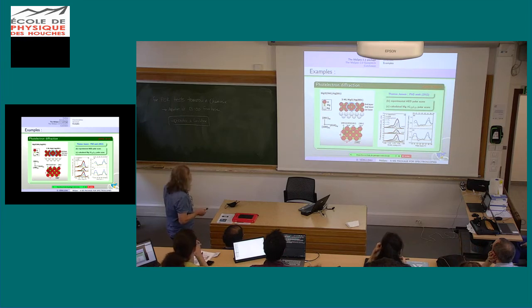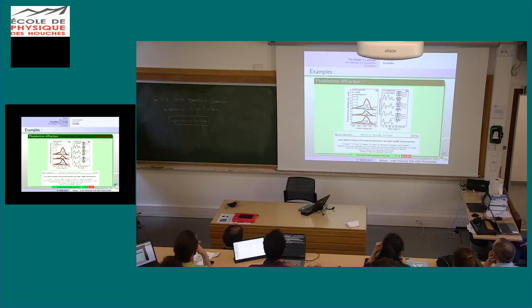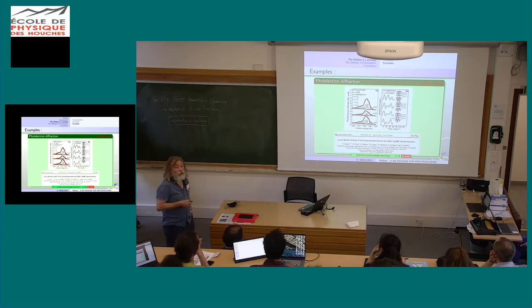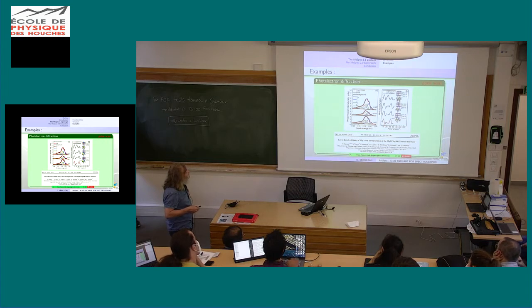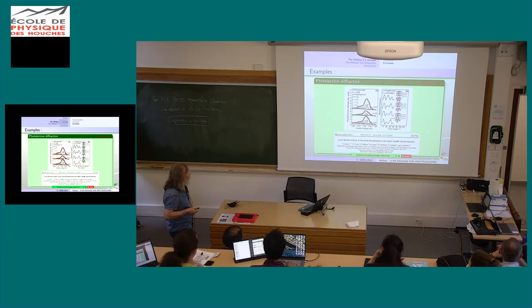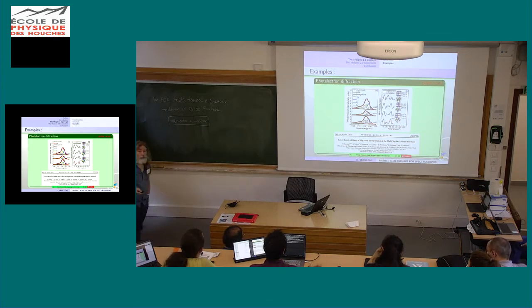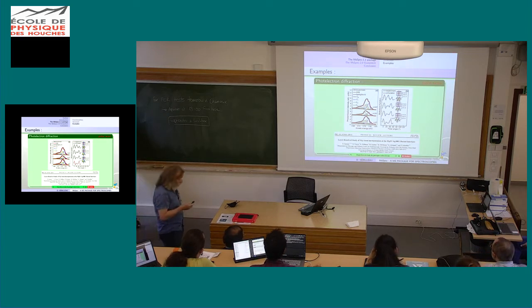The next step is to shine a flux of magnesium atoms onto the material and try to identify where these magnesium atoms will incorporate. In that case, you have an extra peak that appears in your decomposition, called C0 here. We focus on the angular variations of the C0 peak. Experimentally, they are given here, and we make calculations testing different positions of the magnesium atom at the interface. You've got a really good agreement between these two structures. This is an example of use of MSPEC as a photoelectron diffraction structure tool.